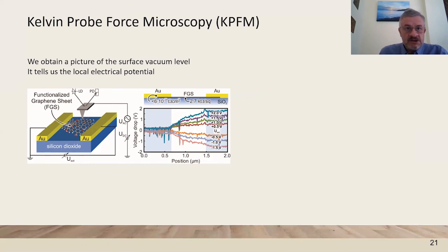The Kelvin probe force microscopy consists of scanning a probe through a sample, and then, since we are measuring the contact potential difference at each point, we are getting a picture of the electrical potential distribution along the sample. In this case, this transistor is biased, and we can say that it's more or less homogeneously distributed. The potential is linearly distributed across the graphene sheet.